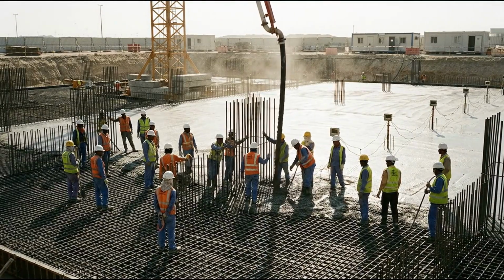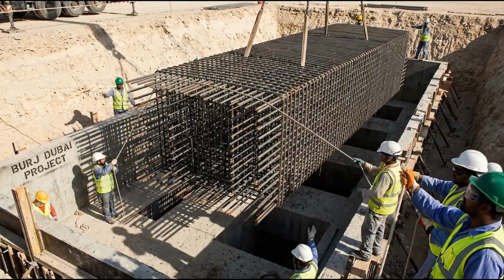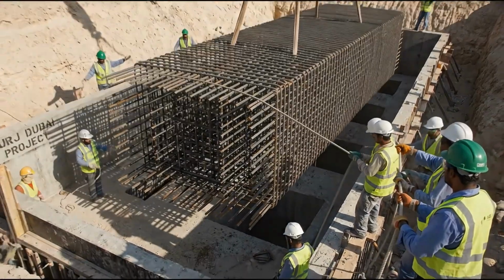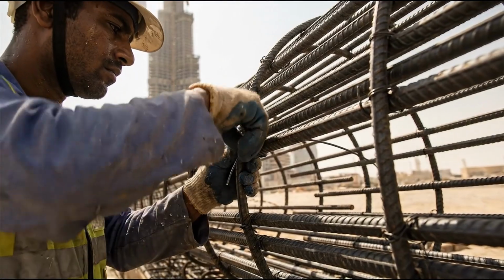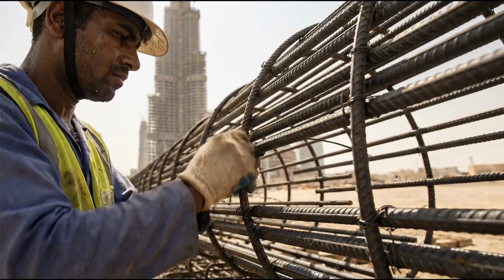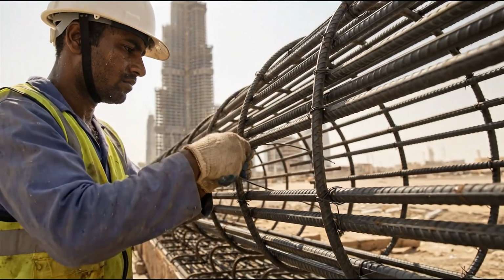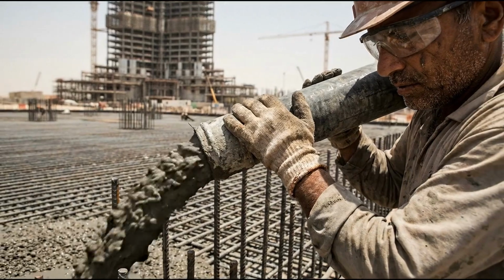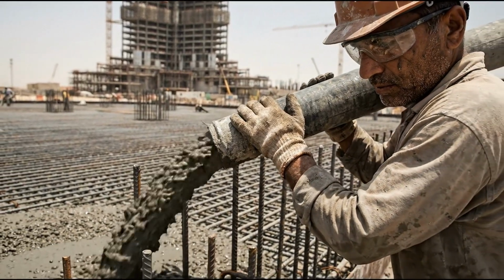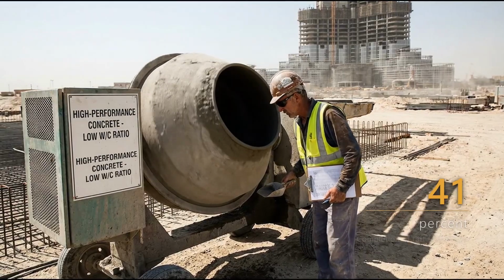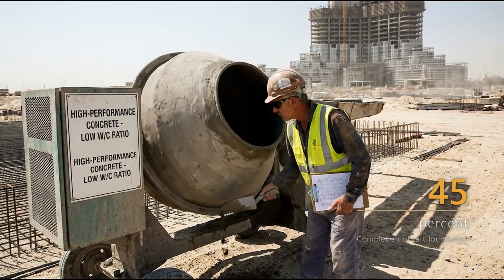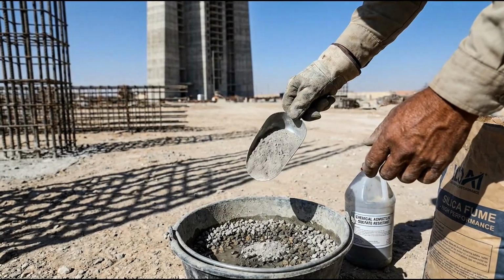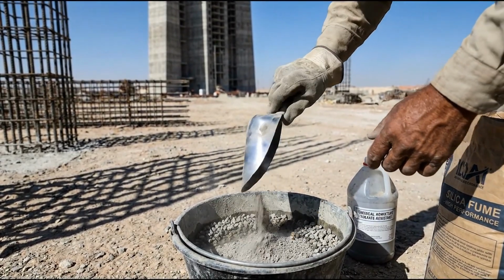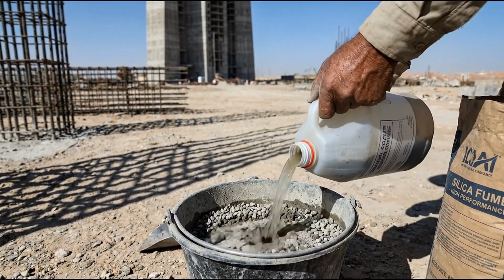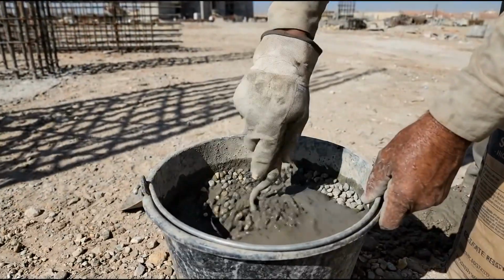Once the hole reached the required depth, a steel reinforcement cage was lowered inside. Thousands of pounds of rebar assembled into a cylindrical skeleton that would give the concrete its tensile strength. Then came the concrete. Not standard concrete. A specially designed high-performance mix with a low water-to-cement ratio added silica fume and chemical admixtures that made it resistant to the sulfates and chlorides in the groundwater.